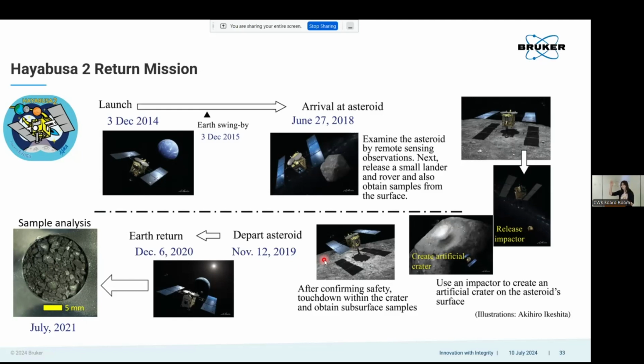It withdrew, and then it sent a small impactor device to make an artificial crater in it. So not only are you measuring what is at the very surface of the material, but you're measuring some subsurface material that you wouldn't have been able to measure otherwise. And so it comes down again and it takes in that material as well. And then it departed in 2019 and returned to Earth in 2020, where we now have these samples.